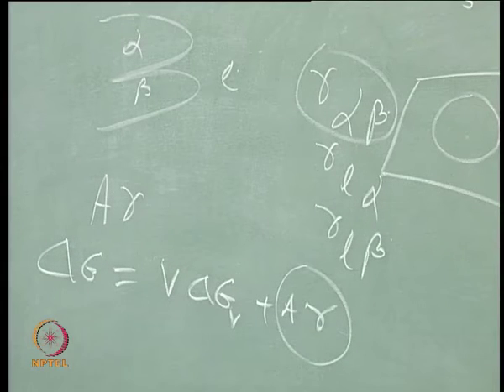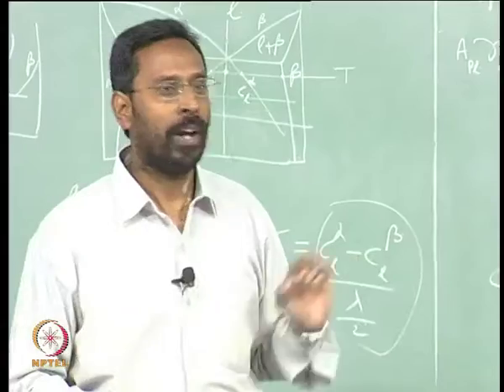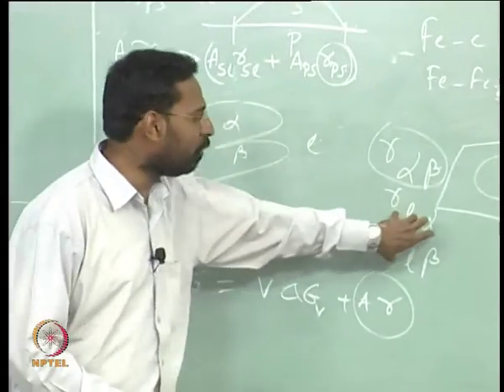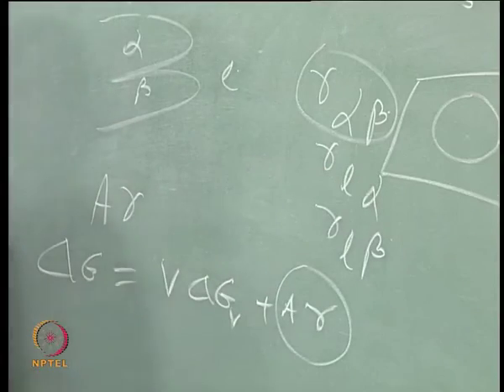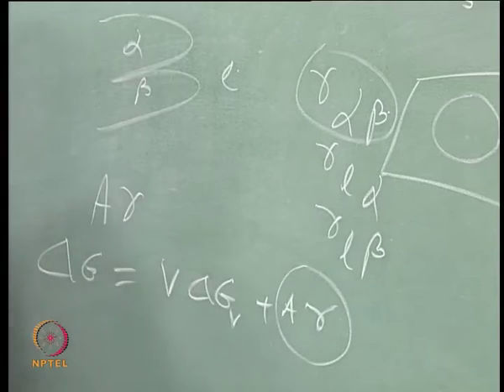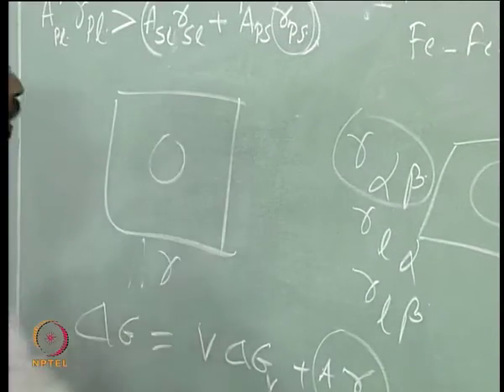You can calculate this or check a handbook of interfacial energies, and you would see this holds true - whenever alpha-beta is smallest, you get lamellar structure. If one of the other two is smaller instead - say alpha-liquid interfacial energy is the smallest - then inside the liquid the alpha will nucleate first.